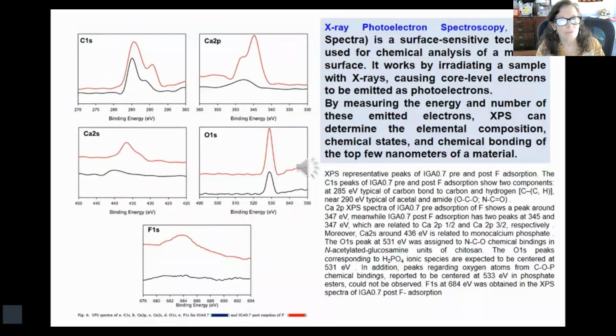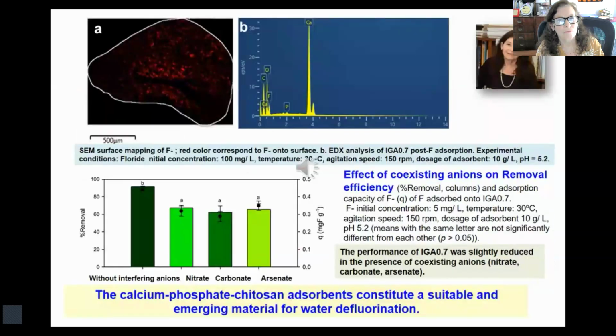XPS, X-ray photoelectron spectroscopy, was also used to characterize the particles. It is a surface-sensitive technique. The red points in the scanning electron microscopy surface mapping correspond to the adsorbed fluoride. The removal efficiency was slightly reduced in the presence of nitrate, carbonate, and arsenate. In conclusion, the calcium phosphate chitosan adsorbents constitute a suitable and emerging material for water defluorination.